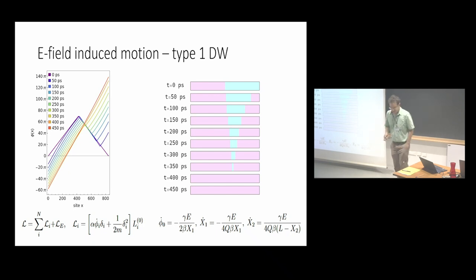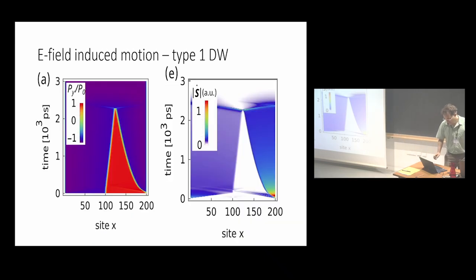Okay, so here contrast is not fantastic, but basically one can see that the velocities are proportional to the domain wall width, to the two outer domain wall widths. All right, and so here basically I'm showing the same thing. This is time, this is coordinate, and initially I had this single domain wall in the middle. I nucleated another one, and it's moving quite quickly initially. And then this red domain shrinks, and ultimately it disappears, and you have some magnon emission here. So all kinds of interesting things are happening.